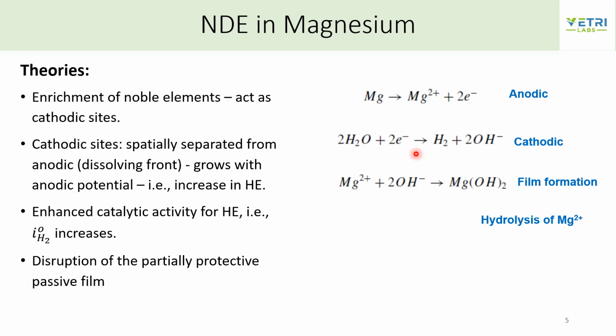So these are the basic reactions that occur during magnesium corrosion: magnesium dissolution, which is anodic, and hydrogen evolution, which is cathodic. Then the Mg2+ reacts with OH- and forms a film, which is magnesium hydroxide. So there is a competition between the film formation and the other reaction, which is hydrolysis of Mg2+. Depending on which reaction occurs, the structure of the protective film is going to change, and it will alter the corrosion or dissolution phenomenon of magnesium.